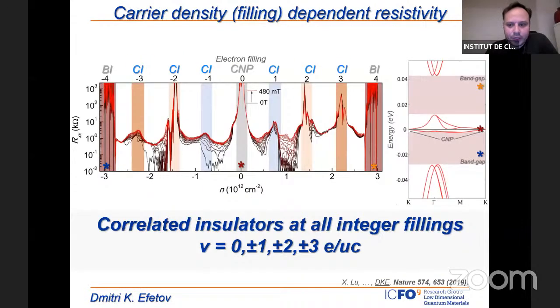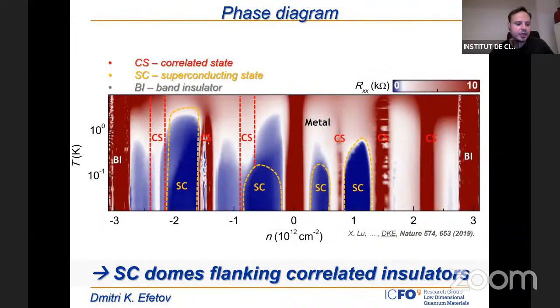Okay, one thing I didn't mention when I talked about the insulators is that the insulators are the regions where we have really high resistance. As you can see, here the resistance goes to more than 2 megaohms, but in between a lot of those insulators, we also saw regions where the resistance basically drops to 0. If we now take a temperature dependence of the very same data, we find that those regions of zero resistance are superconductors, and those superconductors live in between the correlated insulators.